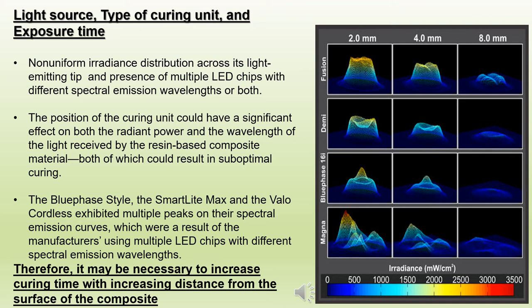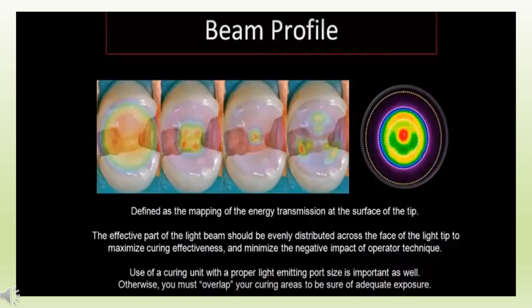Therefore, it is necessary to increase the curing time with increasing distance from the surface of the composite. It is also suggested that the clinician should have knowledge of the beam profile of the LCU in use. Multi-wave LED LCUs have a lack of homogeneity, which lies beyond just the hot and cold spots. Different areas across the tip may have different emissions of violet or blue light. The effect of all this inhomogeneity can negatively affect the micro-hardness and the degree of conversion of the final restoration. A lack of homogeneity should be assumed, and the area should be covered more than once with the active tip to ensure adequate polymerization.